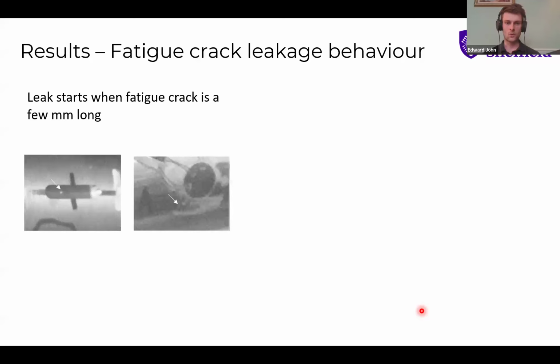So much smaller than the crack in the initial video. And then the jet kind of gets bigger and bigger, and we suddenly have a circumferential crack forming. So that was about 9 load cycles between the crack appearing and the pipe effectively bursting. So what can this tell us about fatigue crack leakage behavior?